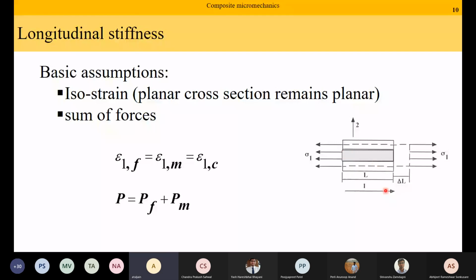If the fiber geometry is not changing as a function of the length, then the planar section has to remain plane. This is the isostrain assumption. Under the isostrain assumption, strain in the one direction in the fiber is equal to strain in the one direction in the matrix, which is equal to strain in one direction in the composite. Okay, but the load is added. If you apply a force P, PF is taken by the fiber, PM is taken by the matrix.